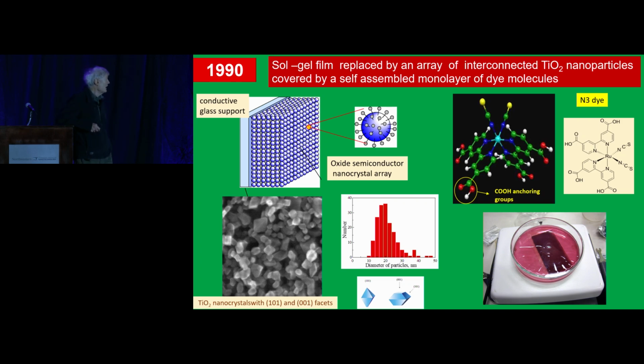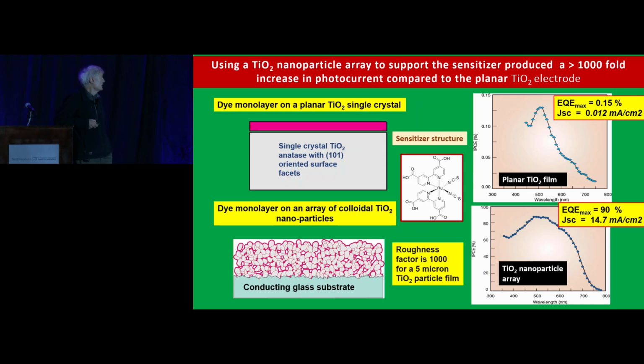However, the question was how do these electrons, which we might eject in these particles, get collected? Our physics colleagues thought we had no chance to collect those, for a very simple reason: TiO2 is an insulator. So how can you conduct electrons with an insulator? They said, look, your concept is not correct. And when we first presented the data in the literature, where we showed 1,000 times enhancement of photocurrent by going from a flat surface to this nanocrystalline film, our colleagues were very skeptical.